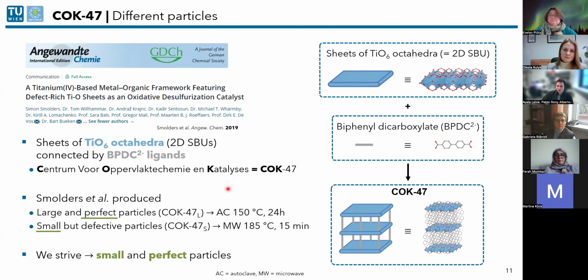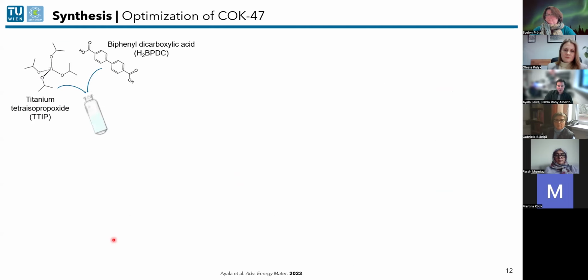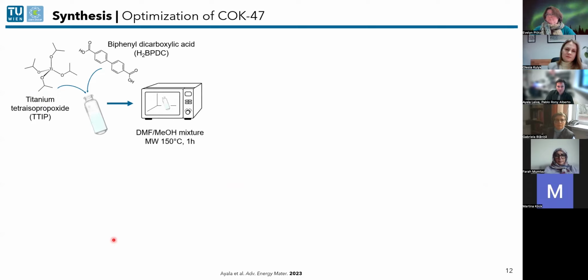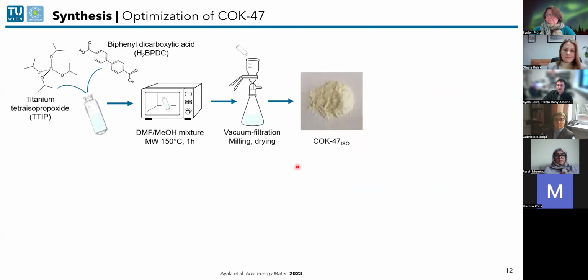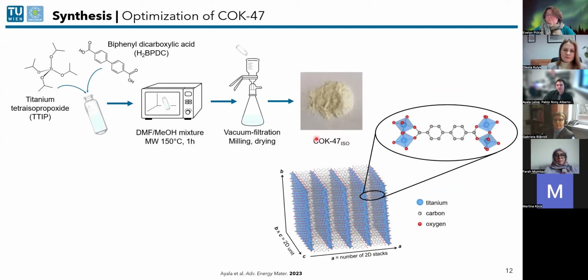So we were wanting to have actually a particle that had these two attributes. So we wanted them small because catalysis is a surface process, but we also wanted to have them perfect because we want to avoid recombination centers. And so this is what we did different. We came up with a different synthetic procedure to make a new COK-47 particle. It is quite simple. So you mix your metal precursor and your linker. You use a solvent mixture, microwave-assisted synthesis, and after some processing, you get this powder, COK-47 iso, because this particle is isotropic in size, okay, and it's non-defective.